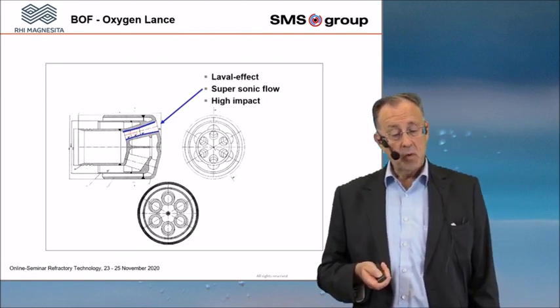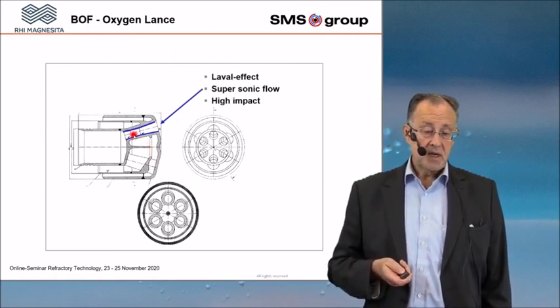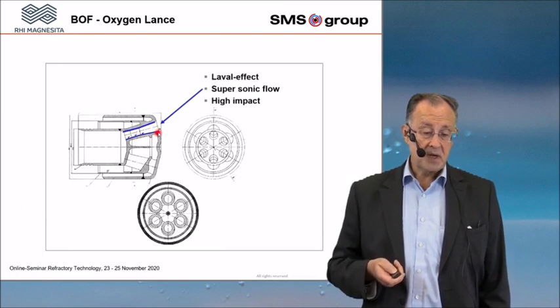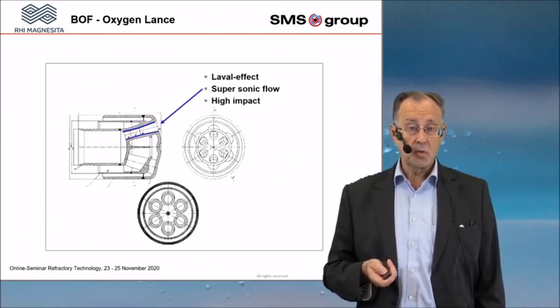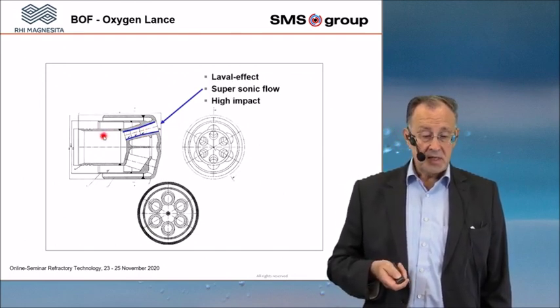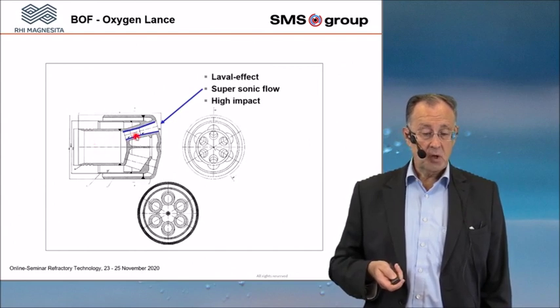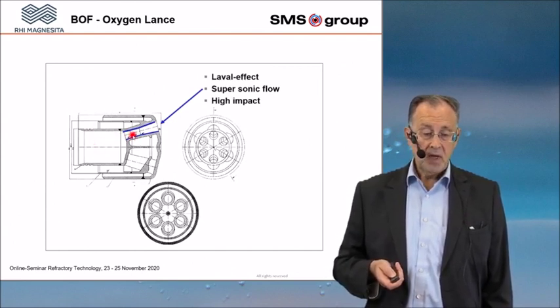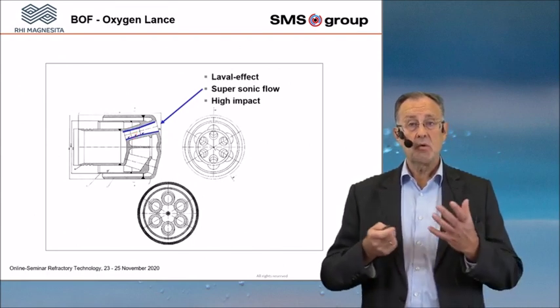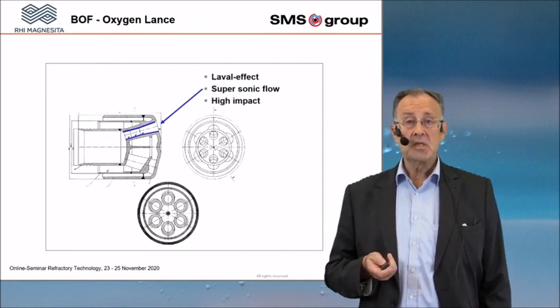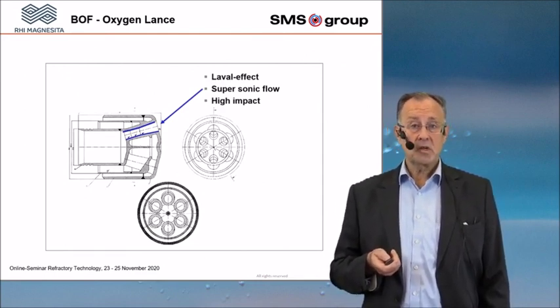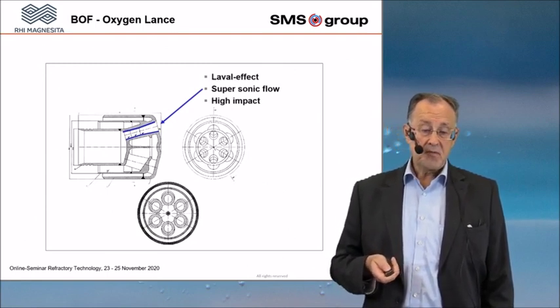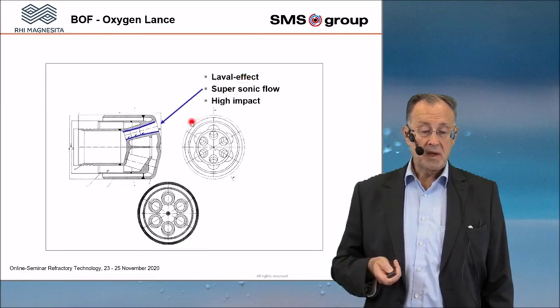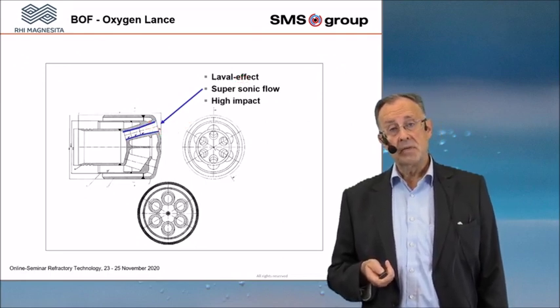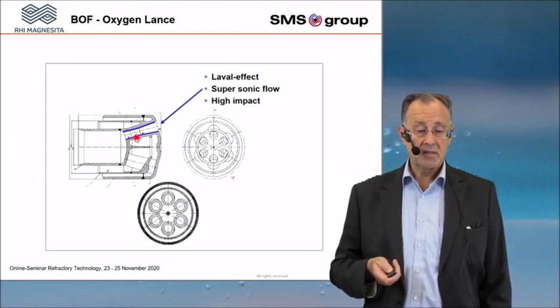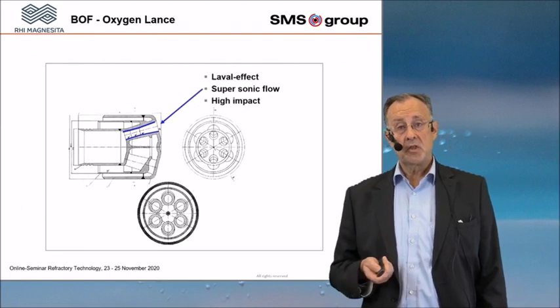The nozzle is built as a convergent cylindrical part and a divergent part. This is important to know, because in the center of the lance, when you come with the oxygen from your oxygen supply and you blow it through the nozzle, then in the cylindrical part, which is a kind of a throat, you have a velocity of max 1 Mach. That means the speed of sound, 1 Mach. And due to the fact, and this was found out by Mr. Laval, when you enlarge the area behind this cylindrical part, in this divergent part of the nozzle, you increase the velocity.